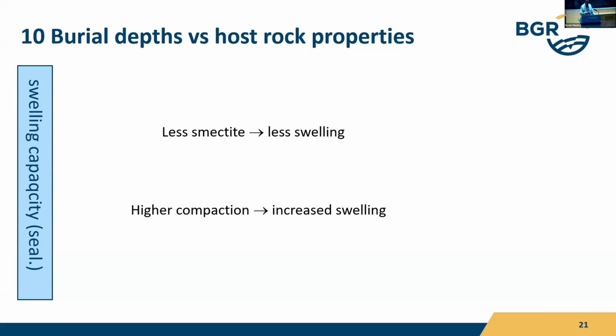What we should know to decide in which direction the arrow should go on the left side is how much, say 10% less smectite, less swelling, would translate into higher swelling pressure caused by higher compaction. So different pore sizes, for example. But this data, as far as I know, is not available so far. And it's actually difficult to measure because you would need suitable samples with different pore sizes. They must be fresh, and the swelling pressure tests of this material are difficult. So it's a bit tricky. That's probably another reason why we don't find any data. But if anybody knows about studies, I would really be glad to have something. I was not able to find any.